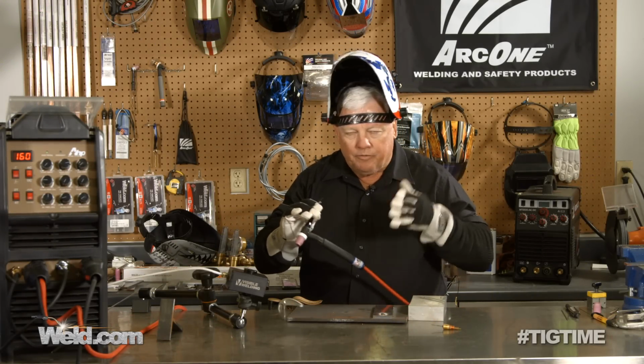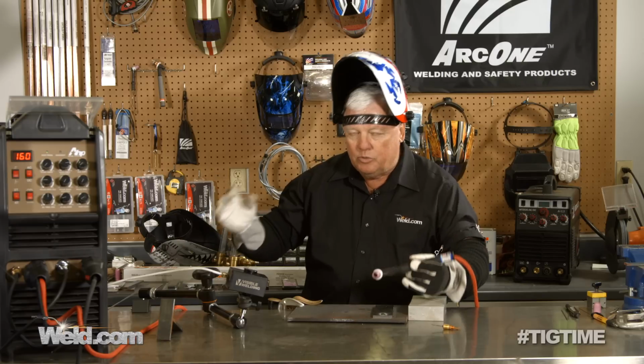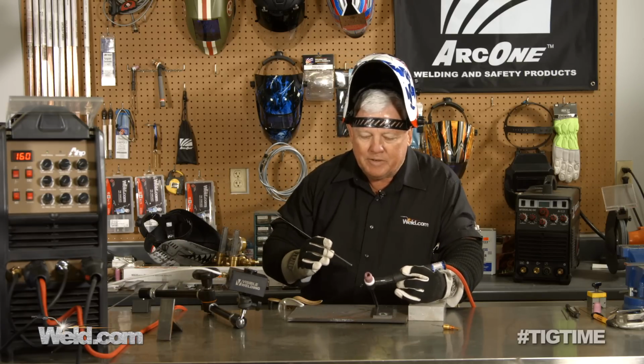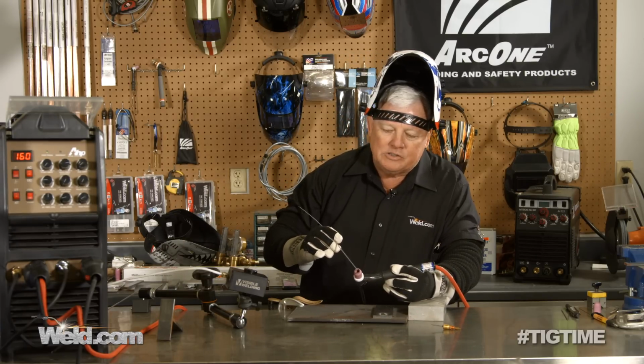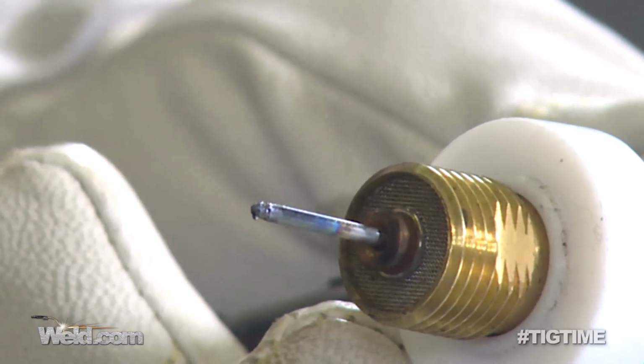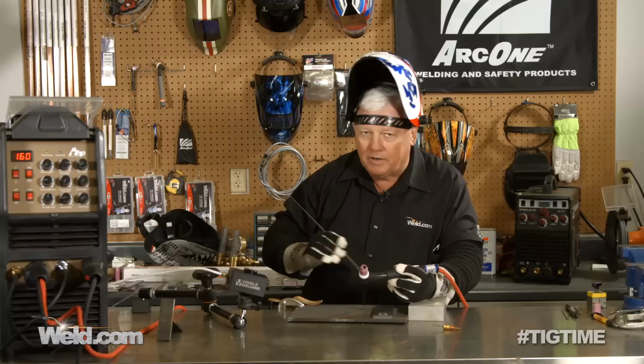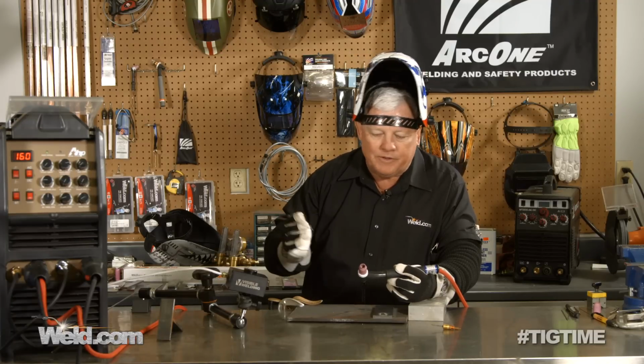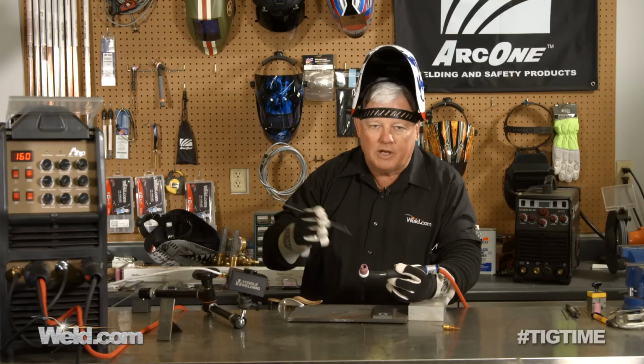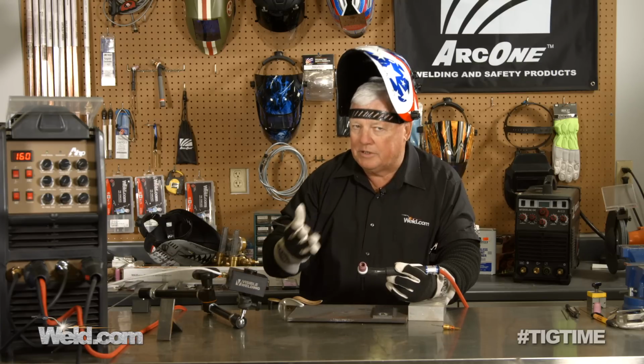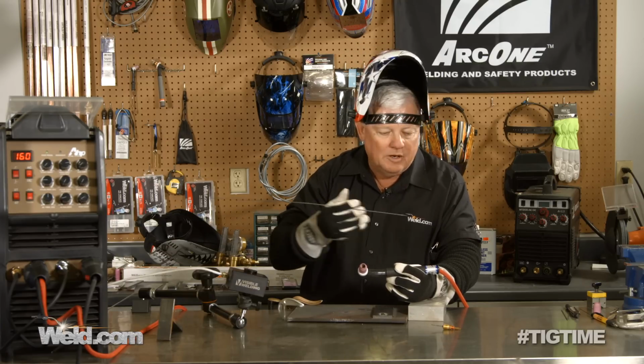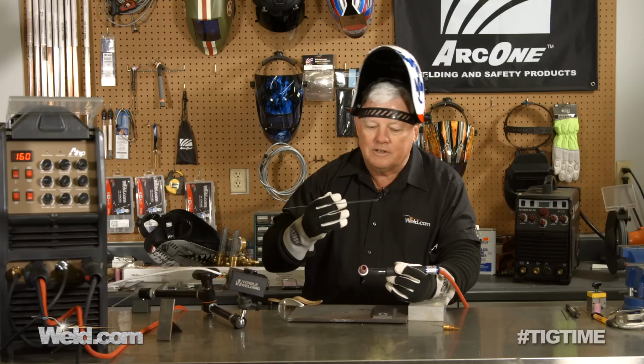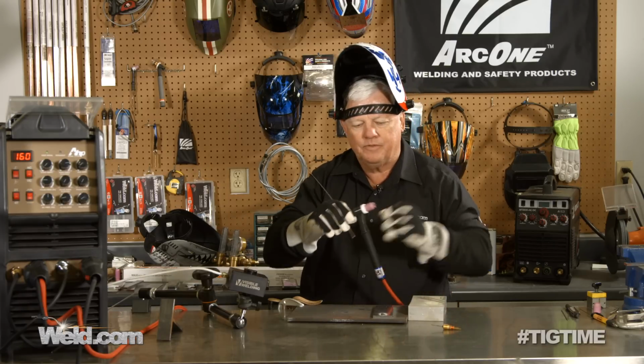I started off with a pointed tungsten, and you can do that with inverter machines, but at 1/16 tungsten, I just lost the tip of it, and chances are there's a little bit of it in the weld itself. The fix for this is a quick fix: just jump up one size, from 1/16 to 3/32. So that's what we're going to do. I'll put the 3/32 in there, and you can see that it's much more stable.